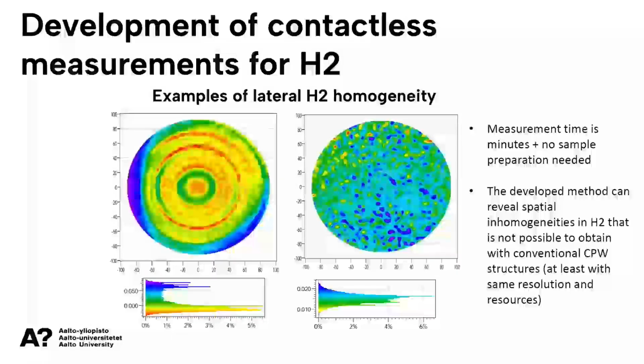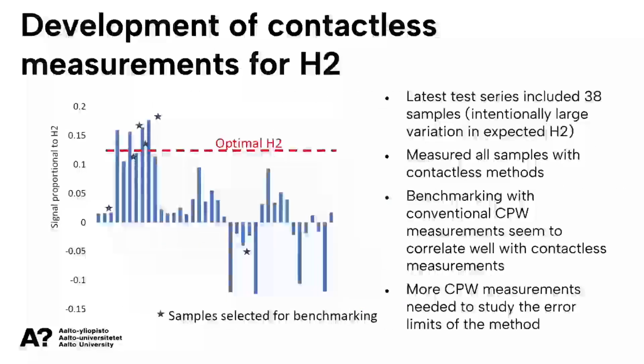So here's an example of the Aalto developed measurements, a mapping of the second harmonic generation property of the wafer, non-contact with high spatial resolution, and it is successful. It takes only minutes to measure per wafer, and extracting this kind of data with this horizontal resolution by the traditional test structure would be extremely tedious, if not impossible. A test campaign has been carried out with a large variety of different wafers with different characteristics, comparing the coplanar waveguide test structure results and the non-contact mapping, and they seem to correlate very well. And now work continues to understand the accuracy and the error limits of the measurement method.